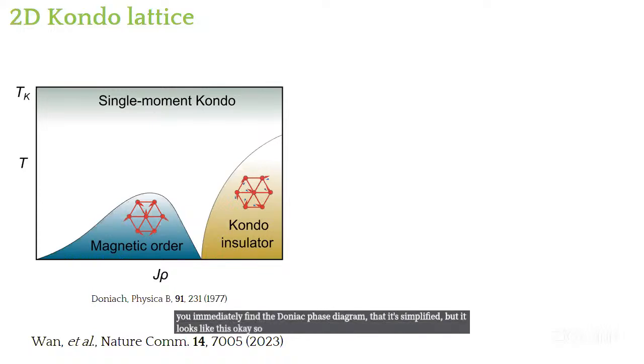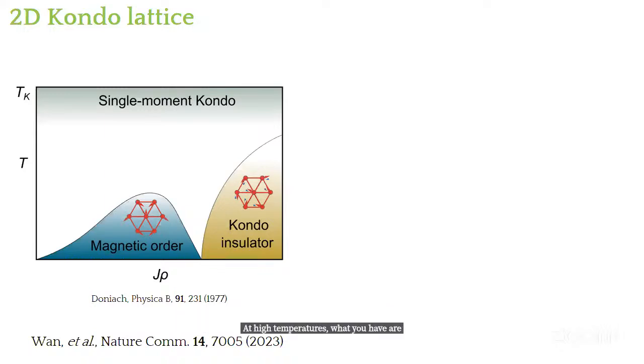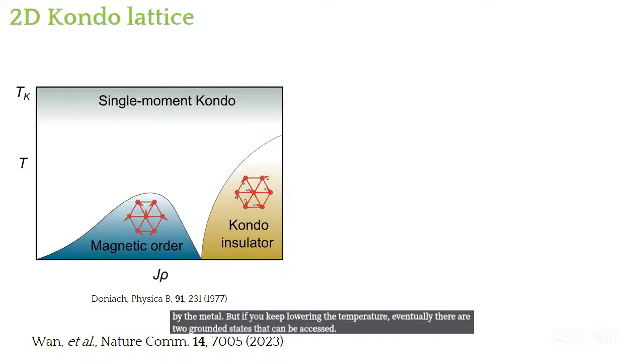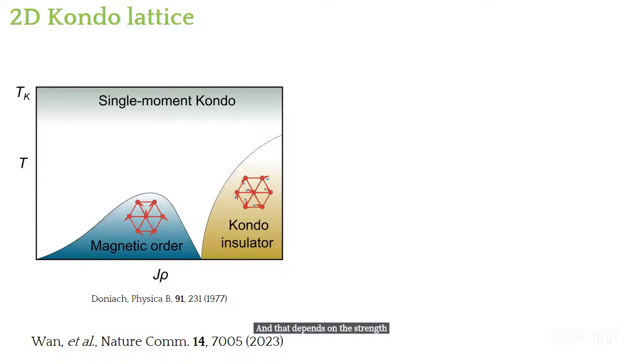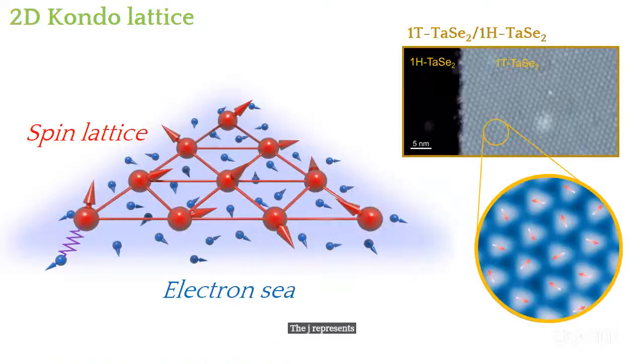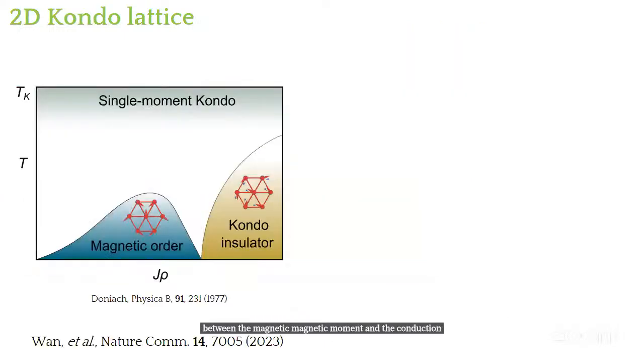Okay, so at high temperatures, what you have are individual magnetic impurities, just screened by the metal. But if you keep lowering the temperature, eventually there are two ground states that can be accessed, and that depends on the density of states and the strength of the interaction between the conduction electrons and the single impurity. So J represents the interaction strength between the magnetic moment and the conduction electron. Depending on that strength, you can get to a Kondo insulator regime, which is a paramagnetic solution in which basically all the spin lattice is screened by the material. And if that's not strong enough, then you access a magnetic order solution, okay?